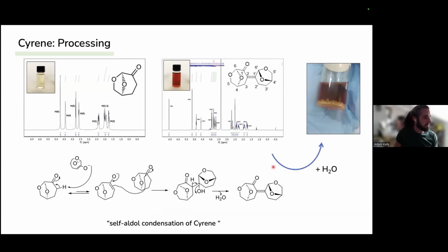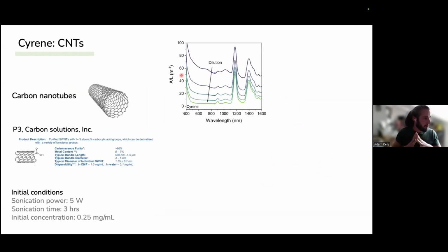Something else that we noticed is that if this dispersion gets wet, if any water gets into it, it causes rapid precipitation, then an exothermic reaction and rapid precipitation of this solid out of solution. So this is pretty important if you're actually going to be processing your material using a sonic tip, because you're going to be creating this along with exfoliating your materials.